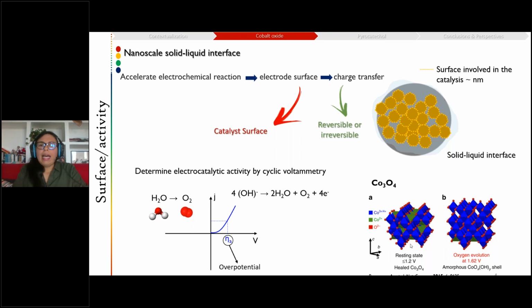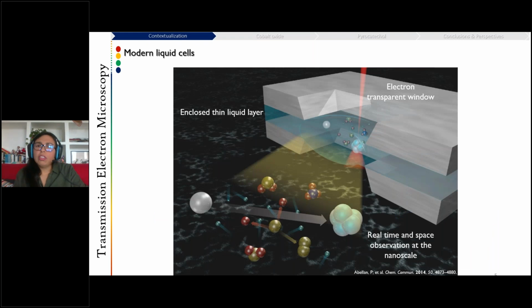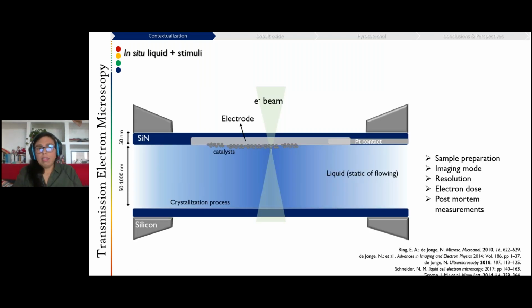And as I will show you, the model material sometimes shows things that we are not expecting maybe. And this led us to the choice of the TEM as the technique of choice, because thanks to the new setups that allow us to enclose a really thin film of liquid and have a really thin electrode, we can see how the electrocatalytic material behaves upon cycling at the nanometric scale, meaning that we have real time and space observation with the application of a stimulus, like in our case, an electrochemical potential, for example.